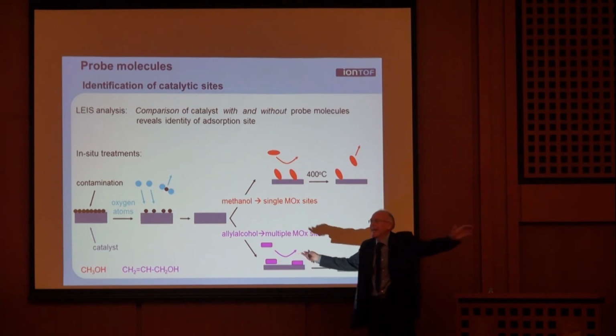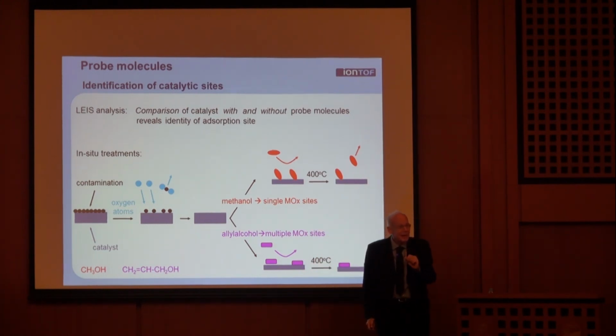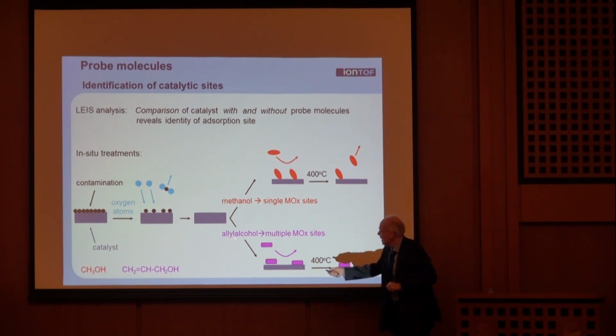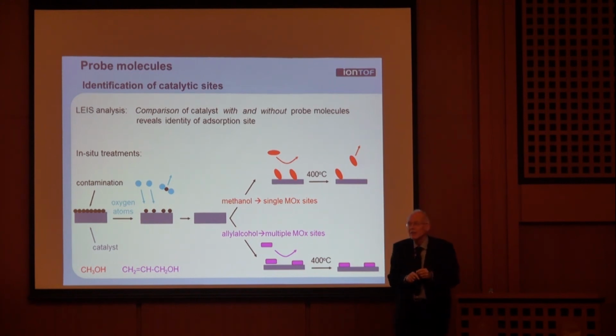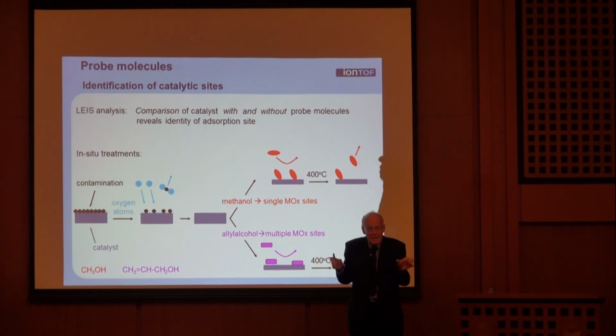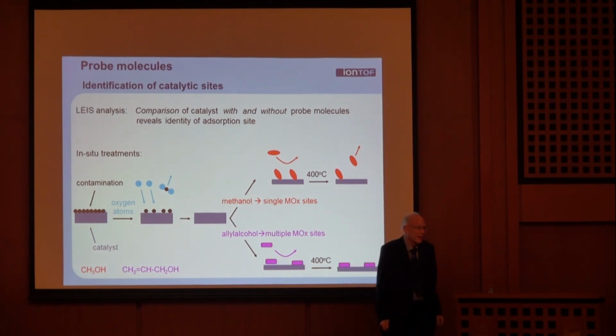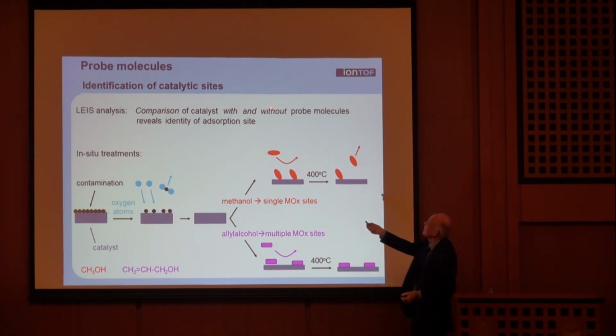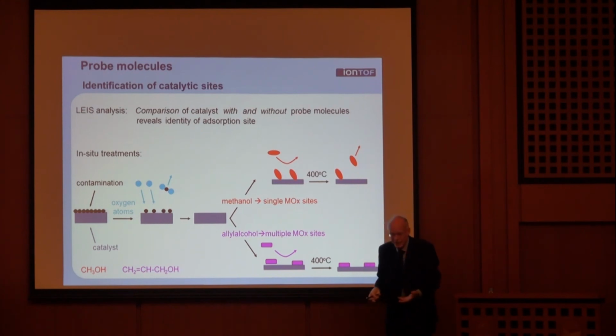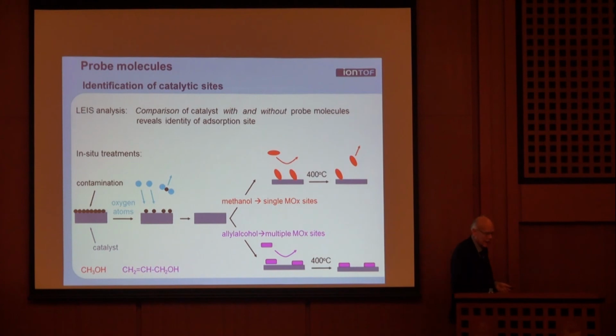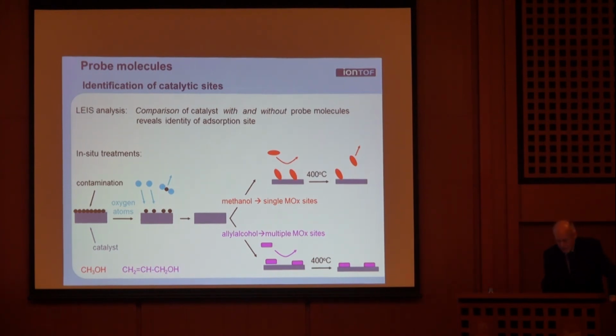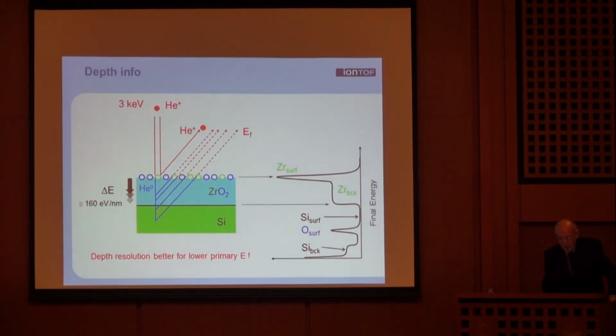Methanol adsorbs just anywhere, so not really fun. The signals of all elements disappear. But allyl alcohol needs two sites. Because of that, you can find out how many of these vanadium cations are close to each other, so close that an allyl alcohol can bind to both of them at the same time. And when it adsorbs, I have monolayer sensitivity. When it sits on top, I don't see what's below. So the change reveals, with and without the molecule, that with the molecule I don't see what is below. And so this way helps me to learn things about the activities.